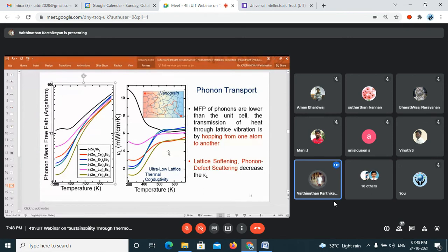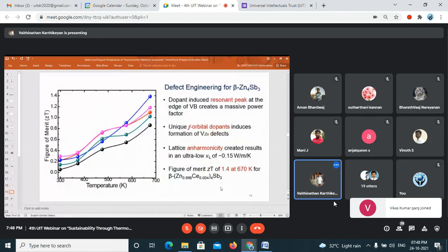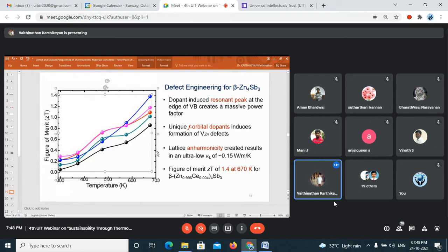This both means the same. So to conclude for this material, you can see the ZT of the doped material is very high compared to the undoped. Through defect engineering and the novel doping technique, we observed the highest ZT at 670 Kelvin for this particular material.